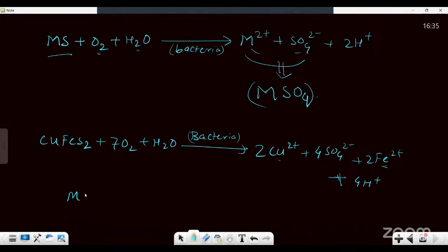So Fe3+ ion is going to act on the metal sulfide, giving M2+, Fe2+ and elemental sulfur. So in the process, a lot of Fe3+ ions are required in order to oxidize the metal sulfide. If bacteria is not present, the Fe3+ ion concentration will gradually deplete, it will gradually lower down.